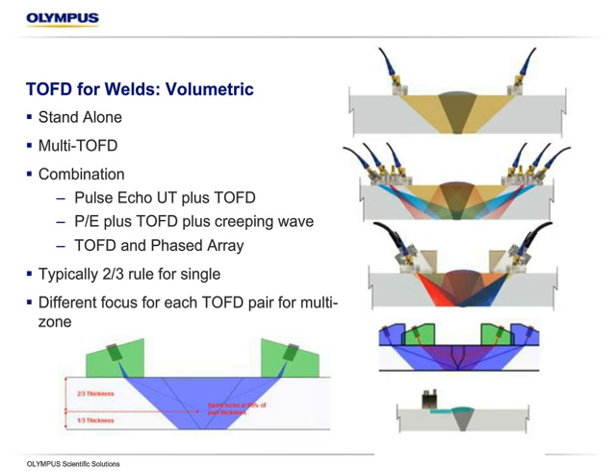Also, lots of multi-TOF inspections. As we get thicker, that 2/3 single probe is not going to give us full coverage. So we'll position multiple sensors at different spacings and different focuses in order to give us coverage of a thicker component. And then all kinds of combinations, especially since the codes in North America require the coverage of those dead zones. So we can put phased array with TOF, we can put simple pulse echo shear wave transducers with TOF, or we can use creeping wave transducers to cover the top dead zone. It gives us that added coverage, and it also allows, if those transducers pick it up, accurate index positioning or volume positioning of the flaw as well. So typically we're going to zone it out with different focuses and do the inspection.